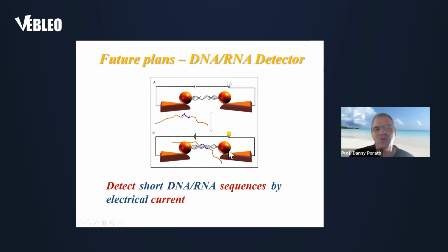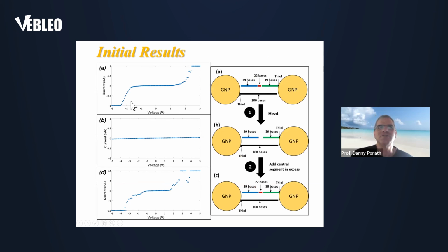And then we looked for what can we do with these measurements, for example, for sensing. So you can see here that there is a dimer trapped between the electrodes with a missing part in the center. And when you bring a DNA which is complementary, then the current will turn on, and that may be relevant for DNA, for RNA. So it's relevant in the context of corona or in the context of cancer. So you can see here a preliminary experiment that supports this assumption.